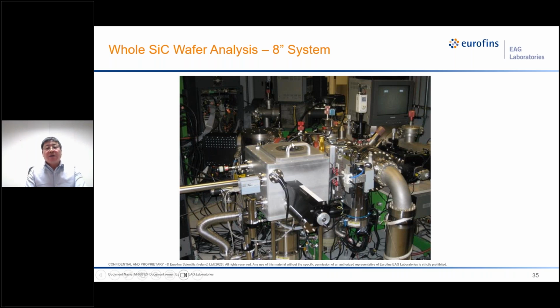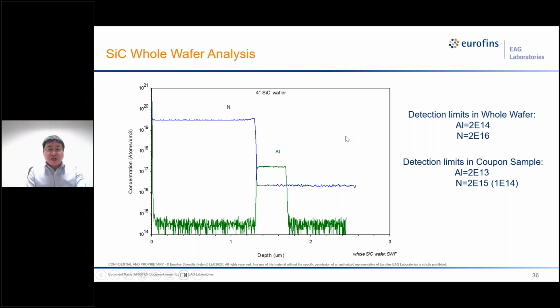So we modified a Cameca IMS-4f SIMS machine. Here is the load lock, which is about 70 cubic centimeters. Because this load lock is exposed to the air, it takes hours of pre-pumping, then we transfer the sample into the chamber for analysis. So we always have a background issue for the nitrogen analysis. And here is the result. For the nitrogen, we have background around 2E16, after hours of pumping. For the aluminum, we can get the detection limit of about 2E14.